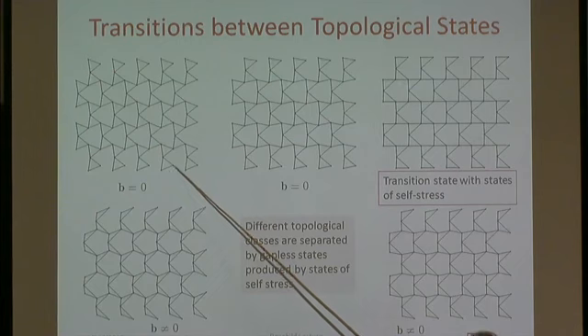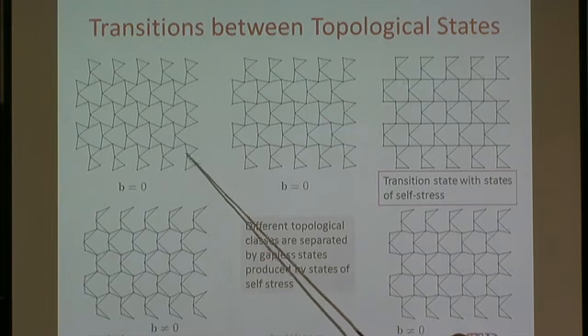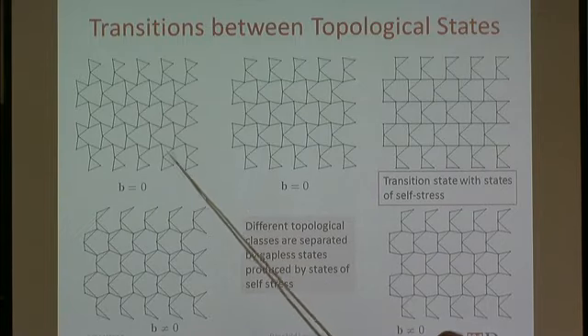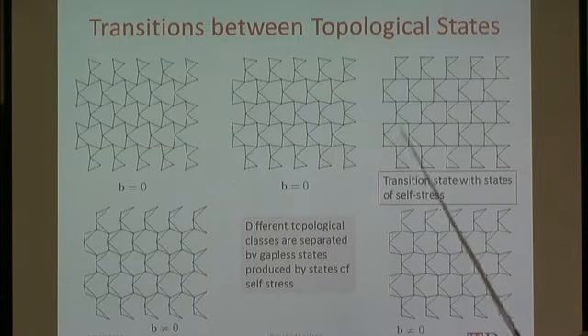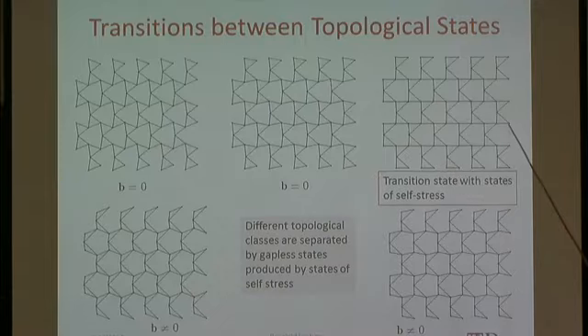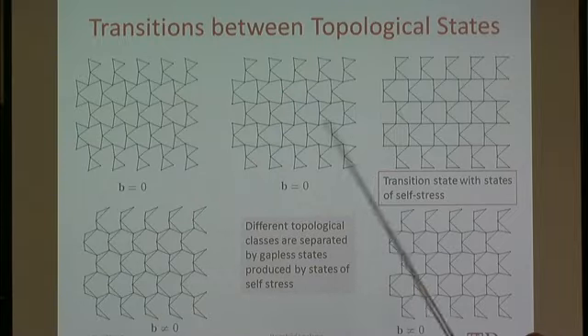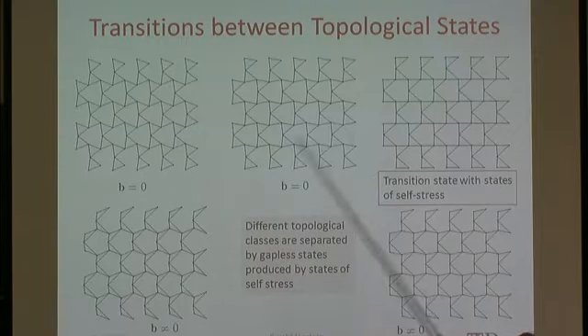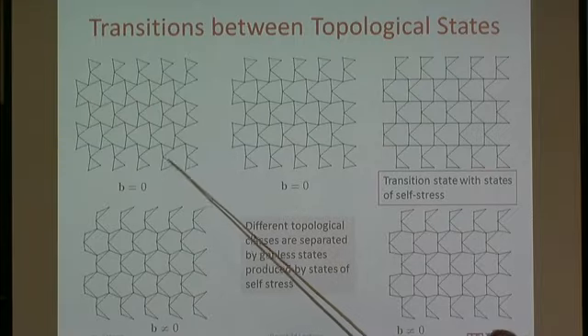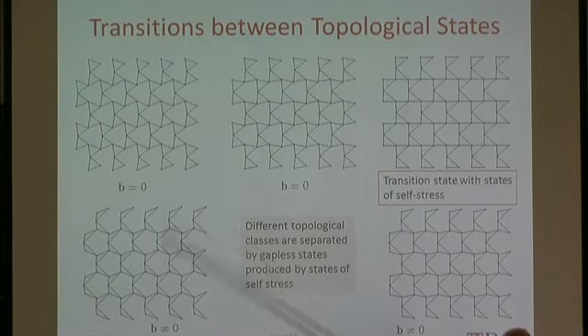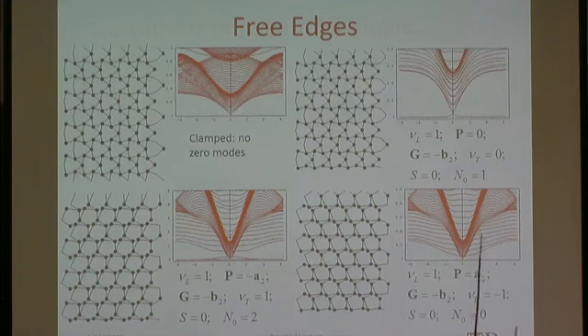So this is the twisted Kagome lattice, and it has no states of self-stress. What I want to do is to continuously distort it, so I introduce a state of self-stress along one direction, and then keep on distorting it so I go to the opposite side. So this guy goes to there by doing a distortion of these things, and I forget which direction, but I can go continuously from here to the twisted Kagome, or continuously from here to this opposite thing. And these two guys have different topological charges, and I can then ask what are their surface modes looking like.